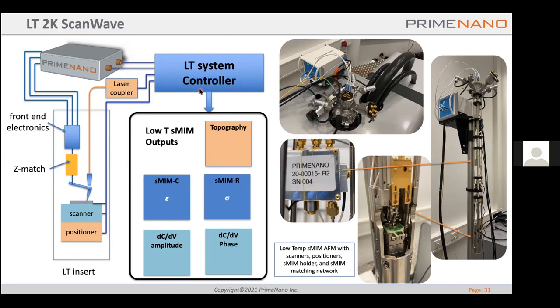In one scan, people can get topography and the sMIM C channel and R channel, corresponding to permittivity and conductivity. People can also apply AC and DC voltage to get dC/dV amplitude and dC/dV phase. The AFM itself uses a laser interferometer to detect the deformation of the cantilever, so you can keep a constant height or constant force to do the scanning. On the right is a photo of the installed system. We have the microwave electronics here, and the insert is in the cryostat. Here is the front end electronics on the insert, and here are the AFM stage, sample, cantilever, laser fiber, and match network.